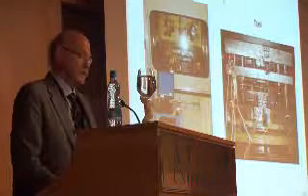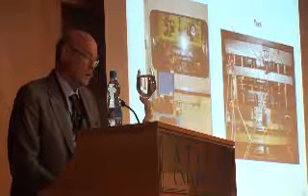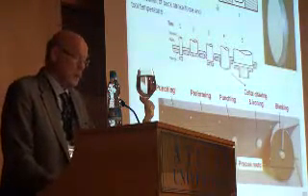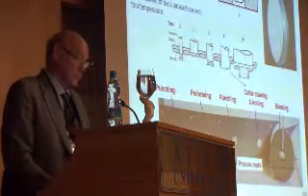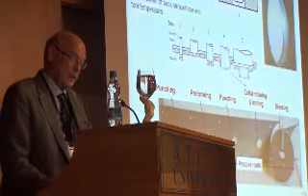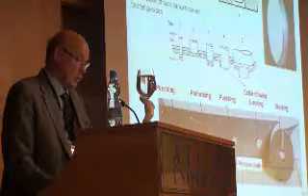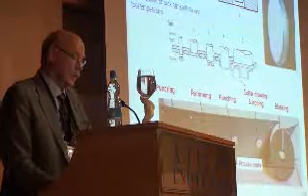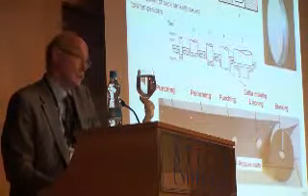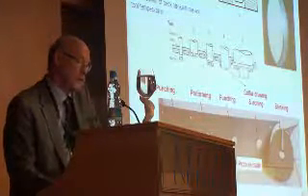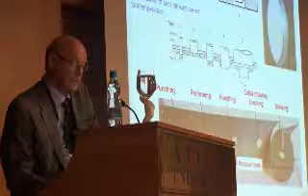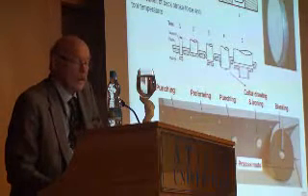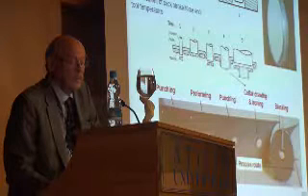We did end user tests with several of our co-workers, among these a company in Denmark, producing stainless steel pumps. And there we tested in a progressive tool for forming this cap: punching, deep drawing, and punching again here, and then a collar drawing combined with an ironing operation of heavy reduction, 30%. That's shown in detail up here. And finally blanking the component. It's process number 4 which is critical. If you use a bad lubricant, you see you get scoring of the workpiece and galling.